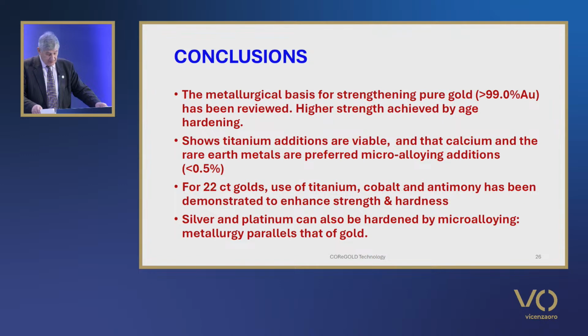Commercial alloys are available and jewellery is being made in these alloys. The advantages and pitfalls of such alloys for jewellery production have been summarised. The extension of this approach to hardening of 22-karat golds has also been reviewed, where the use of titanium, cobalt and antimony are the preferred additions, mostly as microalloying additions. Hardening of silver and platinum by microalloying has also been reviewed, and their metallurgy parallels that of gold.